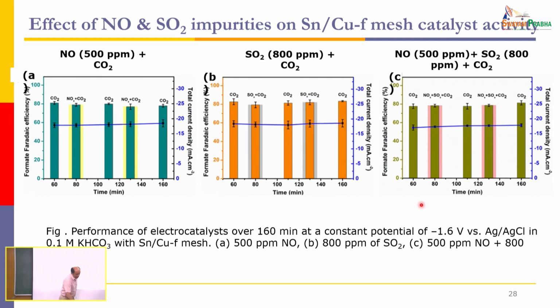And so we had the same catalyst, if you remember. The way we have done the experiment is, first take a solution, purge with CO2, then apply the voltage and reduce it to formic acid. So the Faradaic efficiency is 80%, and to the same solution we have purged NOx,